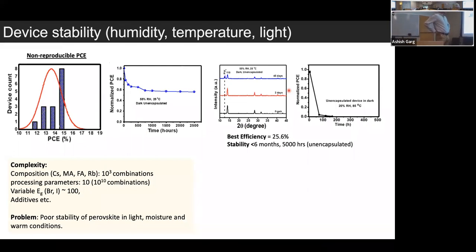spread out. And then with efficiency, of course, when you do measurements under high humidity or high temperature, you see the formation of secondary phases like lead iodide, and they lead to a serious drop in efficiency as a function of time. There are ways to deal with it. People have tried a variety of compositions and varying process parameters.